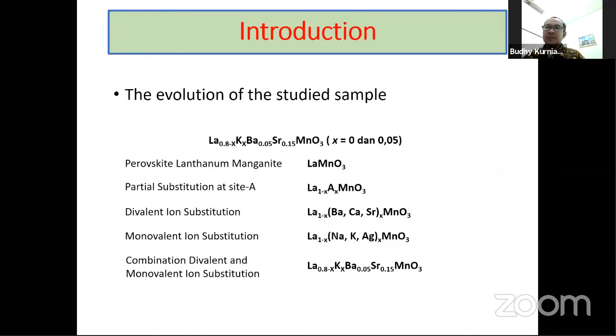Since in our sample, we have some derivatives of the sample. First, the parental compound is LMO, lanthanum manganese oxide. It is a perovskite lanthanum manganite, and we modify this sample with partial substitution at the A sites. It means at the lanthanum site, with two kinds of substitution: divalent ion substitution or monovalent ion substitution.